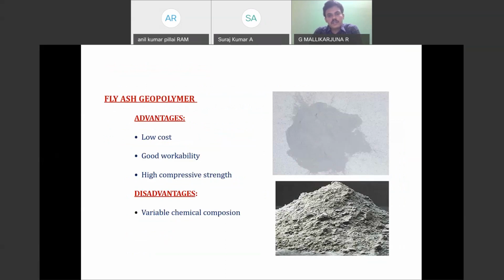For the fly ash based geopolymer, one advantage is low cost and good workability. The fly ash particles are already spherical, and they improve the workability of your concrete, and we get high compressive strength. But this compressive strength depends upon the concentration of the sodium hydroxide solution. One disadvantage is the variable chemical composition of fly ashes whenever you collect different material from the thermal industry. Based on your coal source also, the types of fly ashes will vary.